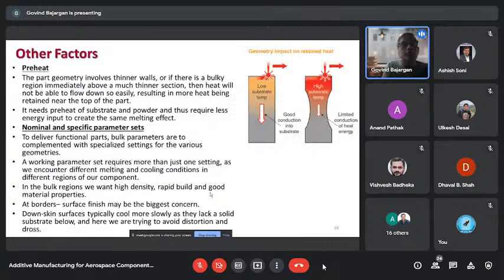Okay, in addition to parameter optimization, particularly what I wanted to communicate is laser power, scan speed, and hatch spacing. There are many other important points which we have to consider while defining the process, like part geometry. If it involves thicker portions sitting over thinner walls, it generally leads to heat buildup because heat will not pass through. These kinds of problems can locally change the thermal gradient, and this may lead to residual stresses and all those things.